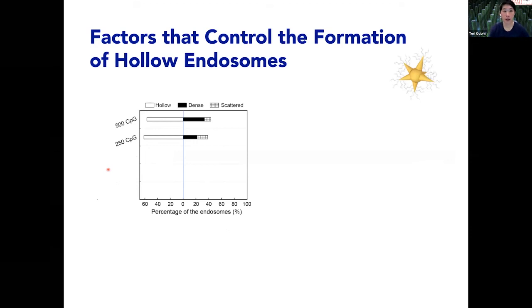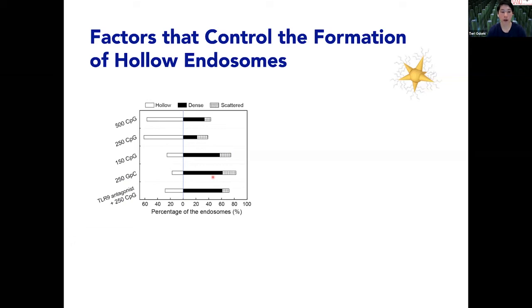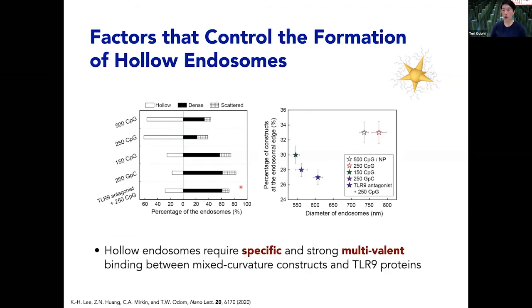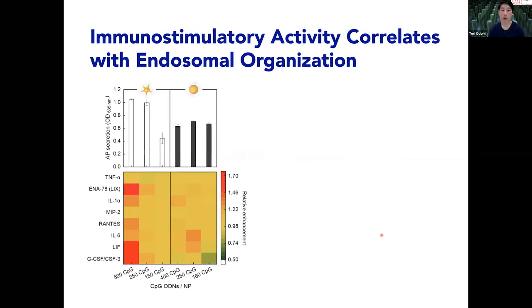And so what are the factors that control the formation? Well, clearly you need to have the targeting CpG bind to TLR9. If you have less CpG, then you increase the amount of the particles that are in the middle. Also, if you have non-targeting, then you mostly get these dense endosomes. And then if you block the TLR9, then again, you get these dense endosomes. So this indicates that in order to achieve these hollow endosomes, you need both specific interactions, the CpG, as well as strong multivalent binding. And of course, we want to correlate the distribution of these particles with the cytokine response.